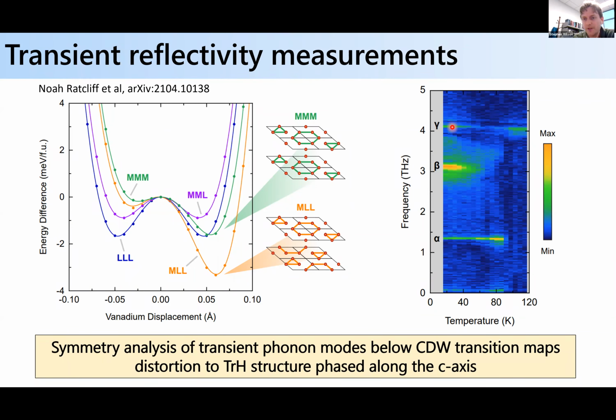And so what they see is that there's some phonon modes that turn on as you cool below the CDW transition, and they can do a symmetry analysis of these phonon modes based off their DFT models. And then they can ascribe that the most likely explanation is what they call this MLL state, which is the trihexagonal structure in the plane, but then out of the plane, basically it's shifted from one plane to the next. So each plane of the system has a trihexagonal distortion, but it's just shifted in the plane one to the next because there's sort of one Q vector that wins out of this 3Q order.